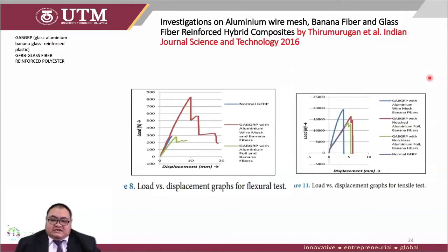For this test, the GABGRP aluminium composite has the highest flexural strength among its counterparts. The GABGRP with aluminum hybrid composite also has the highest tensile and load capacity compared to the other two. GABGRP also exhibits a lower hardness value, which shows that it is less brittle. Thus, it is inferred that the inclusion of banana fiber, laminated with aluminium, influences the mechanical properties.